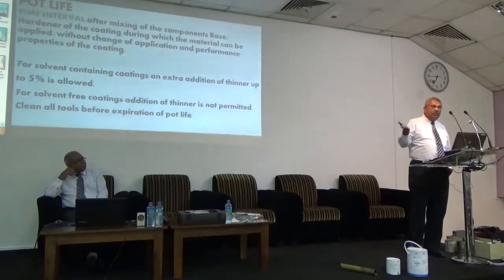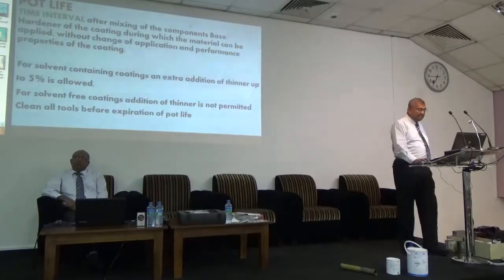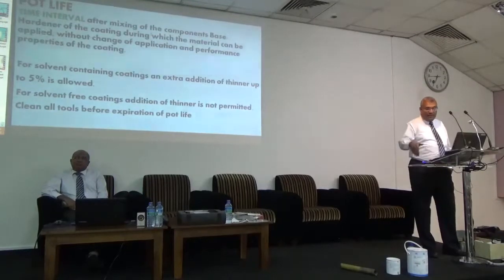So after that, it's not good. You can have failure. So you can put about 5% thinner, if it's not a solvent-free paint, and you finish it. So you have to have knowledge. Okay, after mixing the 4 liters, how much can I apply?